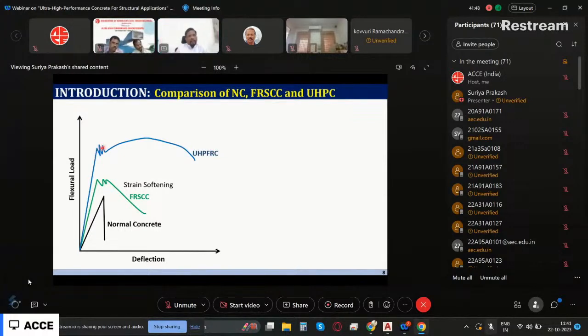And then after cracking, the material will not drop in its capacity, or it will drop in its capacity very slowly. So again, we call this UHP FRC, ultra high performance fiber reinforced concrete. Now whether this drop is going to be flat or very high depends upon how much fiber you are adding and what type of fiber you are adding. So I can make it really high strain hardening or less strain softening also.